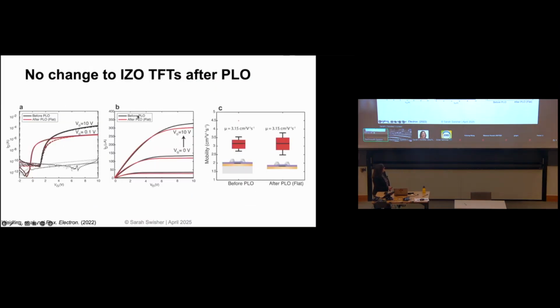For the sake of time, I'm going to skip this part and just show you the device results. So the black is how the transistor behaves in your transfer curve and your output curve before we do that liftoff, and the red is after the liftoff. So you can see that there's very little change before to after, and when we look at the statistics, we see the same thing. This is that mobility.